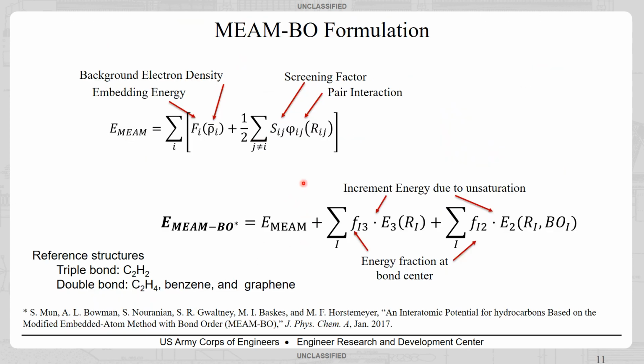So the formulation of MEAM is relatively simple, which makes it quite computationally efficient, especially considering that reactive potential. So here we have your typical pair interaction, where you have between atom I and atom J, your screening factor, which just allows for a bond directionality. But what's important and what's special about the MEAM is this term here, which is the embedding energy. So this represents the energy required to embed an atom into the bulk polymer system.